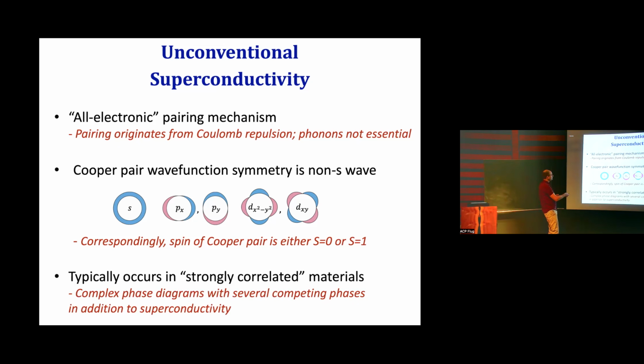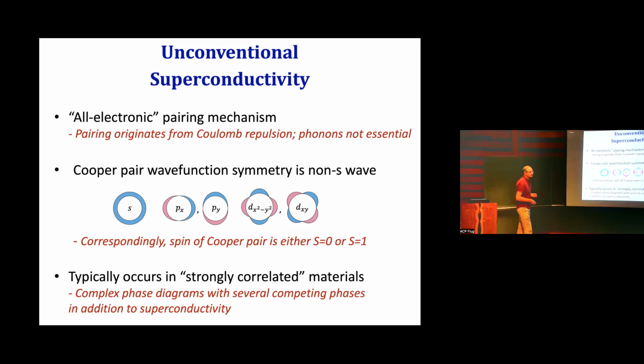Now, most of the superconductors we know of are of the conventional type or the electron phonon type. But we believe that this mechanism is at work in many so-called strongly correlated materials. These are materials where electron-electron interactions are particularly strong, and these tend to have very complex phase diagrams as a result of the same strong electron-electron interactions. Superconductivity is only one contender. There are many competing phases. So yes, if it is spin one, when it condenses it is directional? Absolutely, and I'll discuss that. So the Cooper pair has this extra degree of freedom, of the spin.